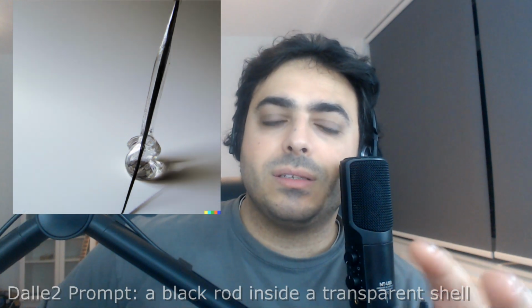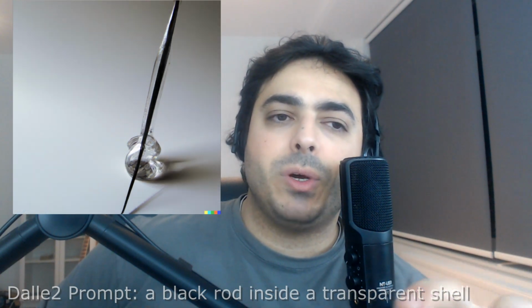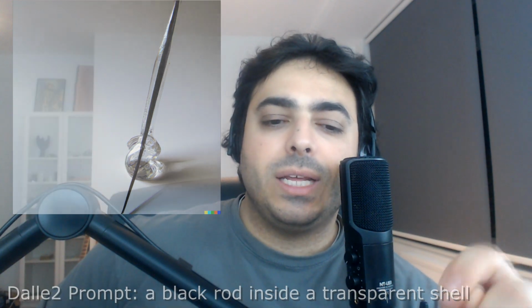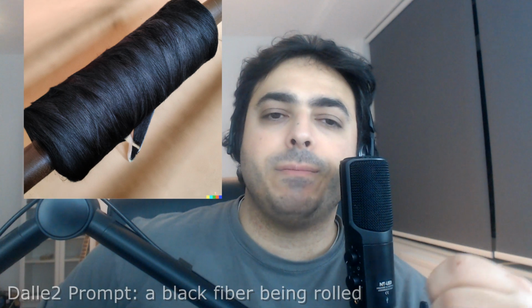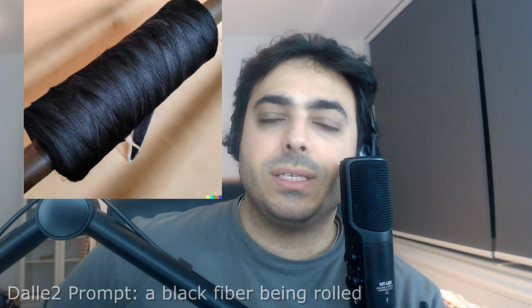At the exit of that last oven, the high temperature oven, the fibers are usually coated with a thin layer of material that is based on epoxy chemistry. That process of coating is in the industry called sizing. That coating has multiple functions, but among the main functions is to protect the fibers from oxidation and from other chemical reactions after processing, to protect them from any damage while handling when these are wrapped again, bundled again, to process further, and to also increase significantly how well the fibers bond to the epoxy later, or to the matrix material later. So later there will be some other material infused between the fibers, and the fibers need to bond very well to that material, so you'll have a significant increase in strength in the component you are producing.